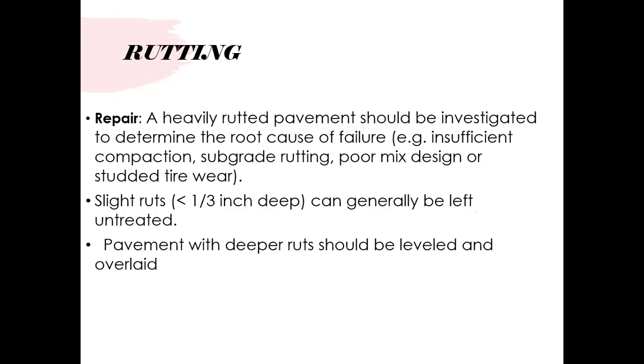There comes rutting. If you have a slight rut, less than 1/3 inch, you don't need to do anything. But if you have a rut depth of more than 1/3 inch, then you have to level it first and then overlay, and that is a structural overlay. Again, this is because of the heavy traffic loading, though most of the time it may be because of other reasons. Whatever the cause, it has to be addressed first, and then you apply an overlay on it.